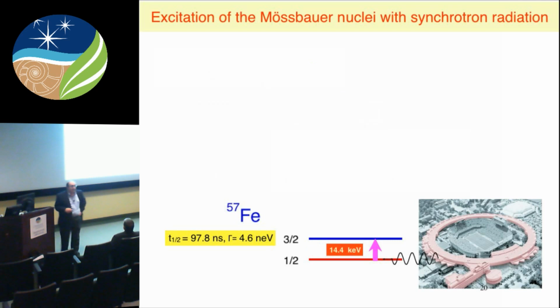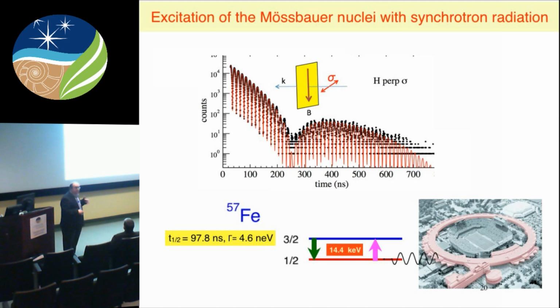Now, the optics for this is, of course, special, and I can say a few words about that later. But the idea is you pump it at this big bunch, and then you let it decay. The red lines that go through this are not interpolation, it's actually the theory. Because the Hamiltonian between photon and the nucleus is exact. We know it exactly, including polarization behavior as well as magnetization behavior. So therefore, we can actually analyze this data quite well.